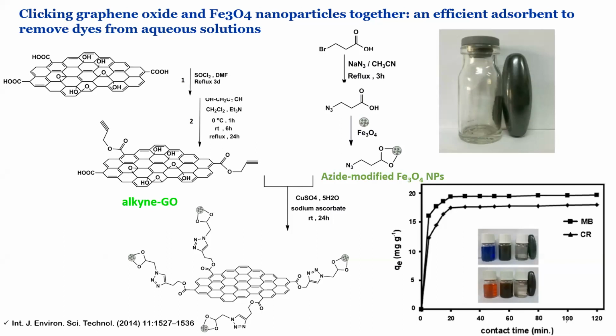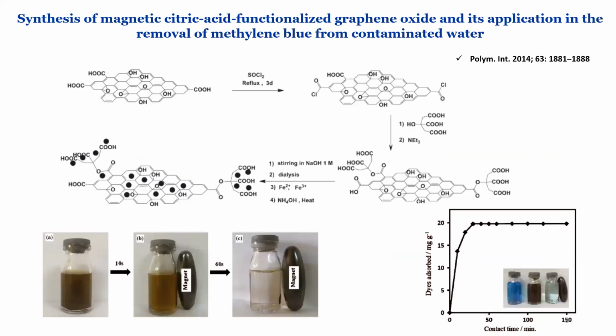Even in SEM images, I could easily see that the nanoparticles were at the edges of the sheets. Since this composite does not have a specific charge, I used a cationic and an anionic dye for adsorption. In the other part of the research, I attached carboxylic acids onto the graphene sheets to prepare magnetic nanocomposite, because acid groups can also stabilize the magnetic nanoparticles. Methylene blue was used for the adsorption, and as you can see in the bottom photo, a normal magnet can easily separate the composite from the water dispersion.